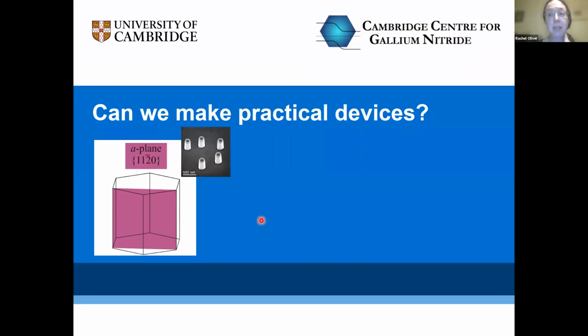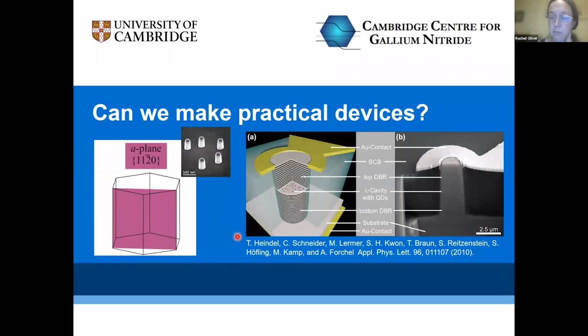Okay, so the only thing kind of resembling a device I've shown you so far are these little pillars, which are optically pumped. If we look at what people are achieving in the arsenide material system, this from the group of Stefan Reitzenstein, then they have some really quite sophisticated devices in comparison. Their dots are in cavities sandwiched between top and bottom distributed Bragg reflectors. They get coupling between the dot and the cavity. They get lots of, therefore, photons emitted from the device. And then they can actually contact to these cavities using these ring type electrodes and electrically pump their devices. So this is a cavity and it's a single photon emitting diode structure, electrically pumped.